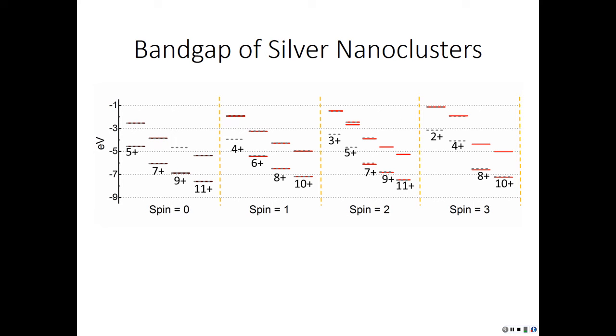Looking at the models that were optically active and had a band gap in the previous plot, we then plotted the band gap, the HOMO-LUMO energy, for these different states, which is here. You can see that for higher oxidation states, +11 compared to +5, both the HOMO and LUMO energy drop, and that's pretty much independent of the spin of the system. So for now, in the interest of time, we're just going to look at these two different spin states, the optically active systems where both the alpha and beta electrons have band gaps.